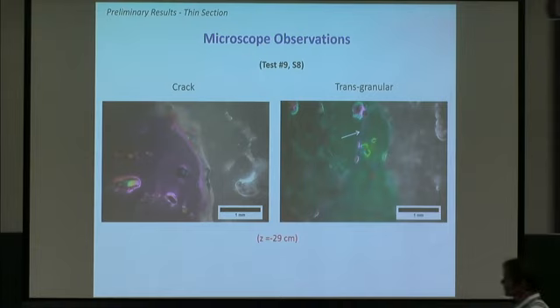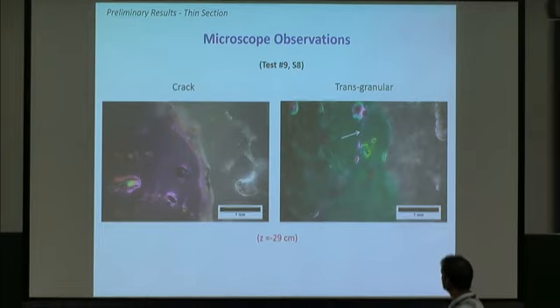If I take these microscope observations and look, we are at the same depth. We can see the crack running over here, and here this is a void, a brine pocket, or could be gas as well, running further here, forward here, and up, and probably looking for a weak zone. What you can also see here is that the crack here is clearly transgranular, so it doesn't necessarily follow the grain boundary.